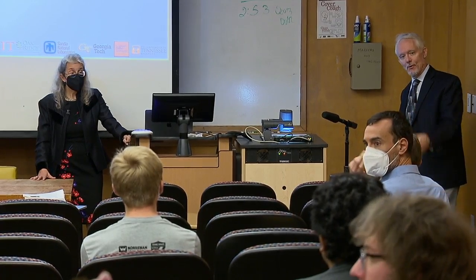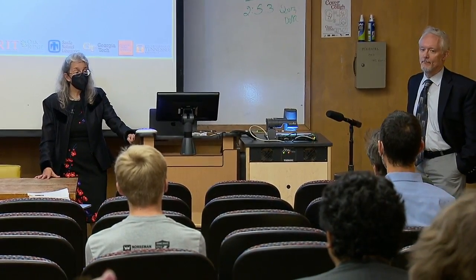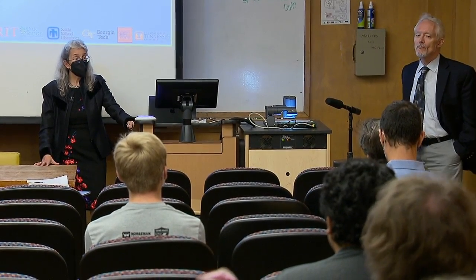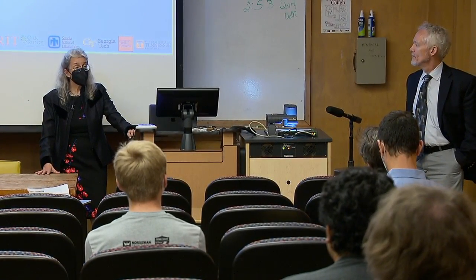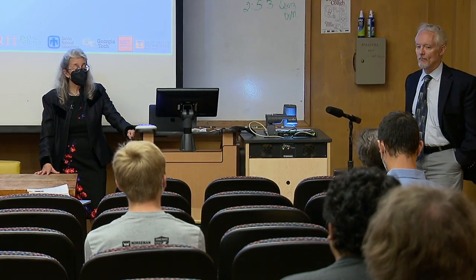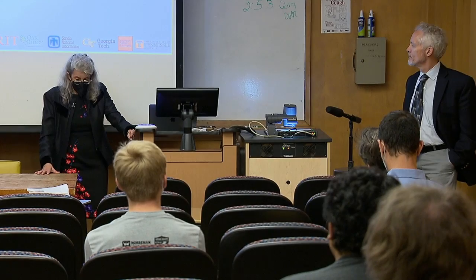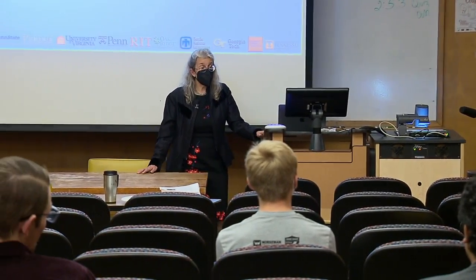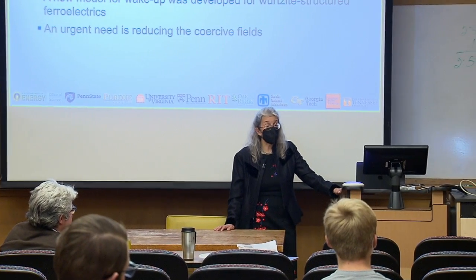I had a couple of detailed questions. What is the rationale, or is there a simple way to understand why you can drive up the solubility limit by a factor of 10 when you go to a thin film? We are growing under conditions that are nowhere near thermal equilibrium. That's probably the first thing. At 200 degrees C, these are strong bonds. We do not have enough thermal energy to take an atom that sticks here and move it a micron away to go find a comfortable position. We're kinetically trapping it into the easiest crystal structure.